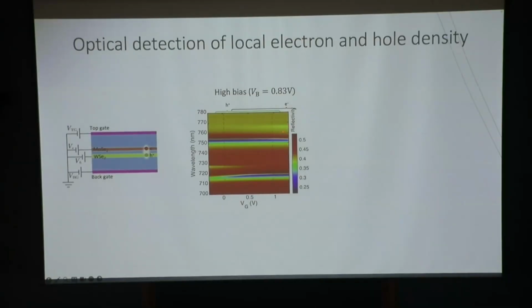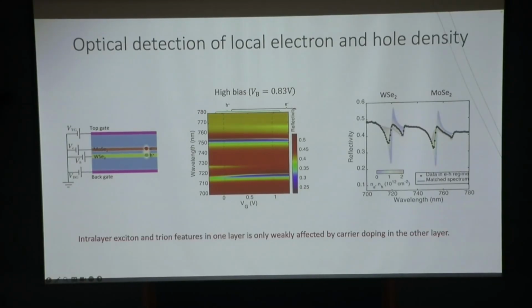Here, electron is doped in the MoSe2 because you have the electron-side trion. In the middle, the electron side has a trion, which means it's electron doped, and the hole side has a trion, which means the hole is doped. So we can directly find that electron and hole are now both injected in the system. And if we quantitatively measure the spectrum and compare with our calibration, we can determine exactly how many electrons and how many holes we have.